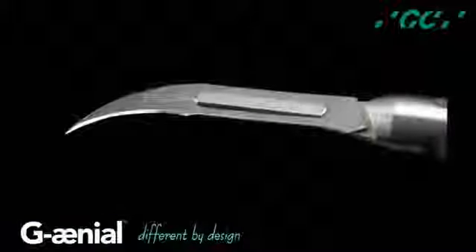Initial polishing is accomplished with a rubber hollow cup, which allows any surface defects to be effectively eliminated. This hollow cup provides additional flexibility for the curvature of the premolars. Any excess polymerized resin material is removed from the interface using a number 12 BD Bard-Parker scalpel blade. A high luster is accomplished using a loose abrasive diamond composite polishing paste with an enhanced synthetic foam cup and a small amount of water.